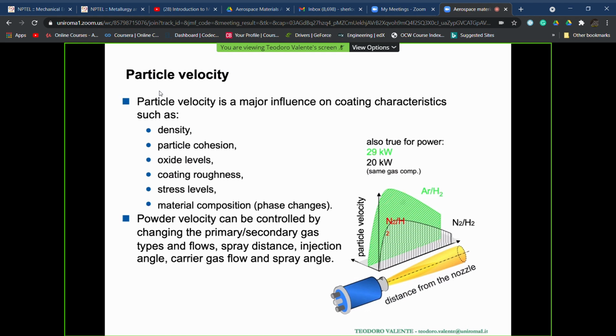relevant impact on roughness of the coating itself, because the splat mechanisms are controlled by the kinetic energy with which the particles can impinge on the substrate, the stress levels, as well as any eventual phase changes inside the coatings, that is materials composition. And the powder velocity can be controlled, that's a guideline, by changing the mixture between primary